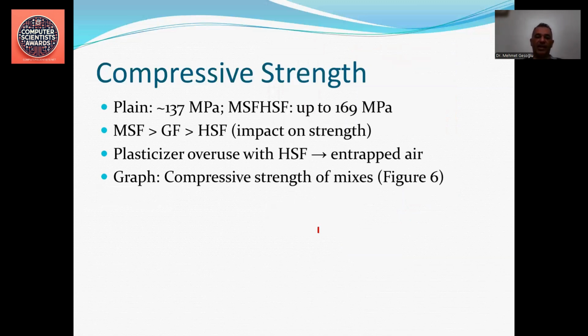The test results have shown that plain concrete reached a compressive strength of 137 megapascal. By using hybrid fiber of microsteel and hook steel fibers, the strength reached at most 169 megapascal. The order of the beneficial effect of fibers ranges from microsteel fiber, followed by glass fiber, and then hook steel fiber on impact strength. This, of course, was observed in compressive strength and flexural strength as well.